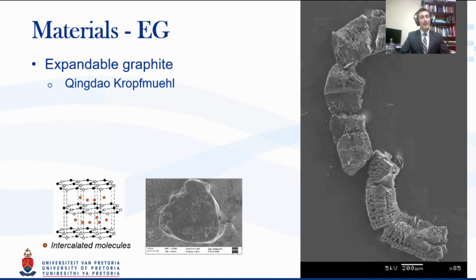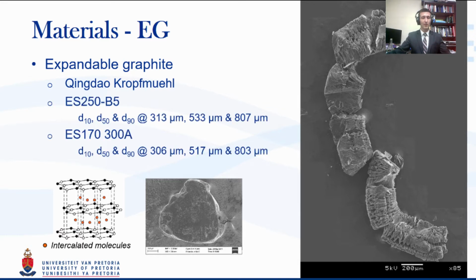One of the things that we discovered, however, was through analysis of these two different materials, although they look very similar on the surface, they have very different structures. What we identified, as you'll find in my thesis, is that the low temperature onset expansion material actually is not as pure an intercalated compound as the other. What it has undergone is an even more excessive level of oxidation.